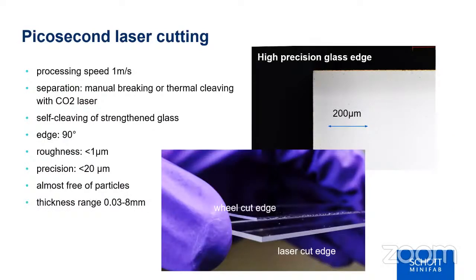We do this with a picosecond laser, at a speed of roughly 1 meter per second. You see here the high precision glass edge, no distortions. Separation can be done by manual breaking, for example, or thermal cleaving with a CO2 laser. Strengthened glass is self-cleaving, so it breaks by itself. The edge is perfectly 90 degrees. We have a roughness in the order of 1 micron. You see it at the bottom.